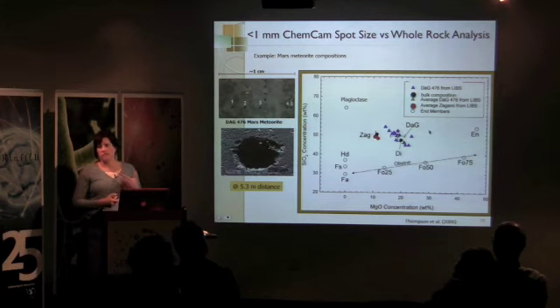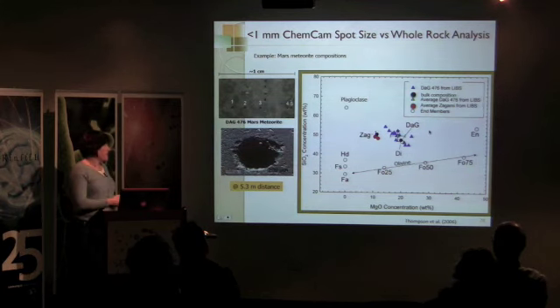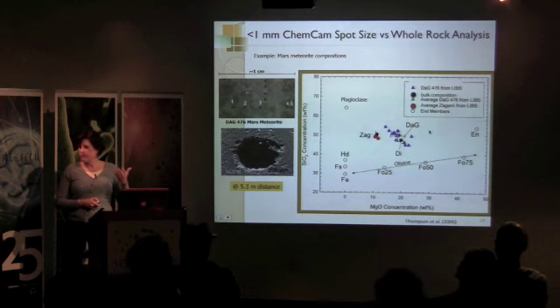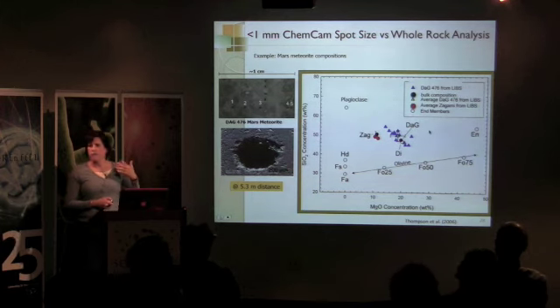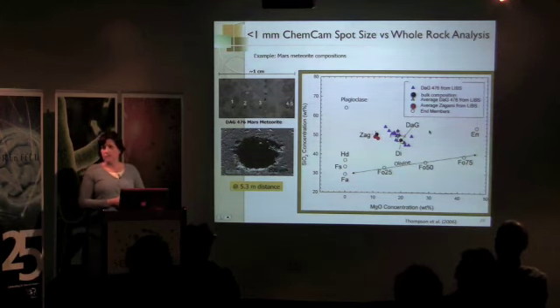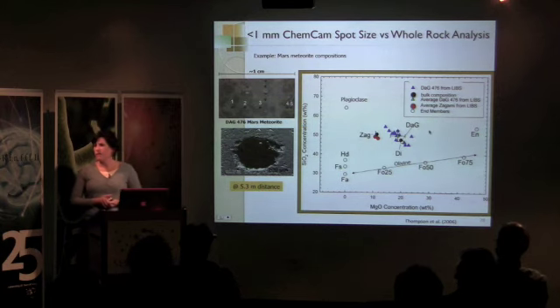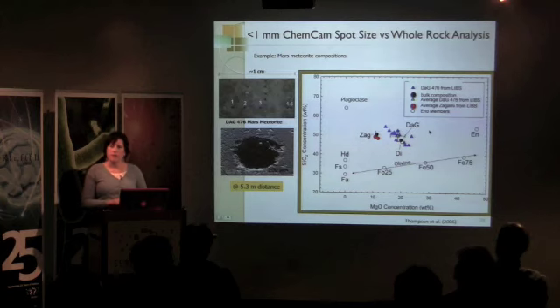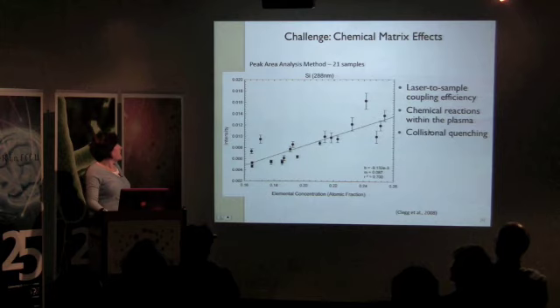And these are two elements that LIBS is very sensitive to. And compare in blue and red different LIBS measurements with, in black, the black circles, which are actually bulk composition XRD from the literature. And so you can see we'll get an average composition. We're sort of falling about what's considered to be bulk composition, but once again, we have to be careful to know where we're pointing our laser and assess whether or not it might be representative of a larger sample. So scale is of concern.